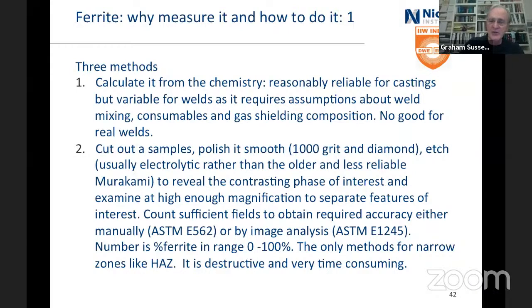Then you count sufficient fields to obtain the accuracy that you want. And you do it either manually, that's ASTM E562, and boy, that's boring, it really is. Or by image analysis, which means you've got to have really good polishing, really good etching, and really good contrast. The number you get out at the end is a percent ferrite in the range 0 to 100. And it's the only method you can use if you're looking at a zone like the heat affected zone.